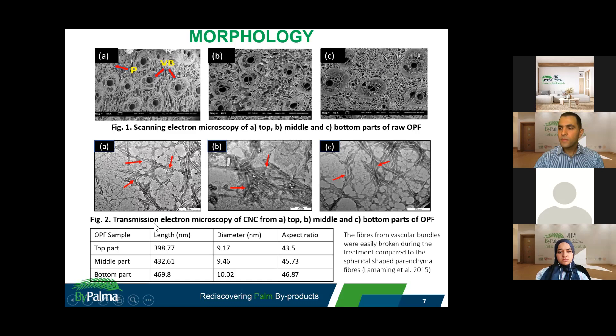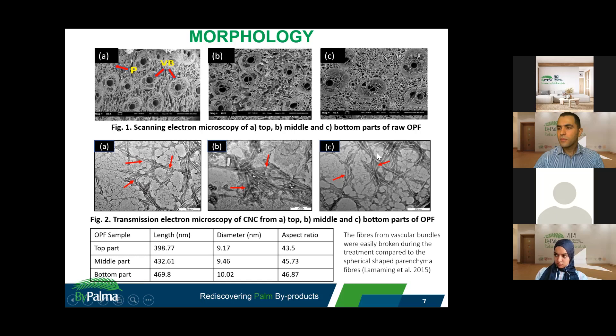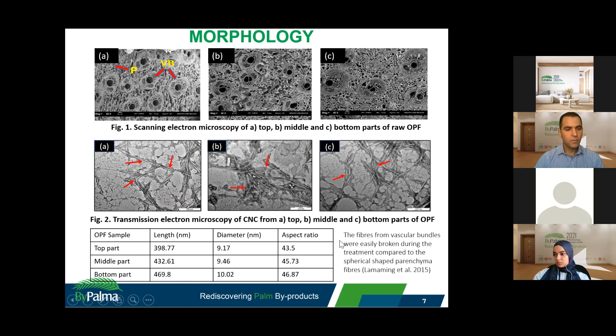Figure 2 shows the TEM images of the top, middle, and bottom parts of CNC from OPF. We can see the cellulose nanocrystals are not agglomerated — they are in individual form and easily measured. We measured the length and diameters of this CNC and found variations across the three parts: the top part has the lowest aspect ratio and the bottom part has the highest. This is because the fibers from vascular bundles were more easily broken during acid hydrolysis compared to the spherical parenchyma, so samples with higher proportions of vascular bundles were more easily disintegrated.